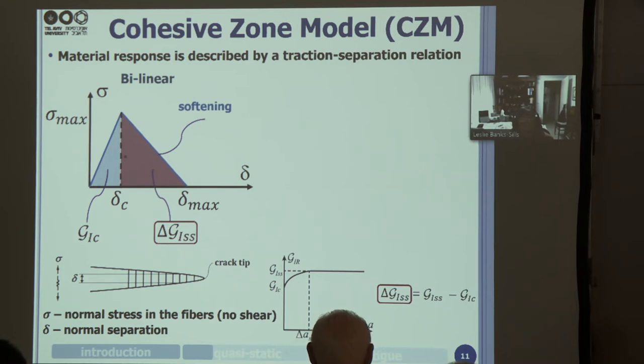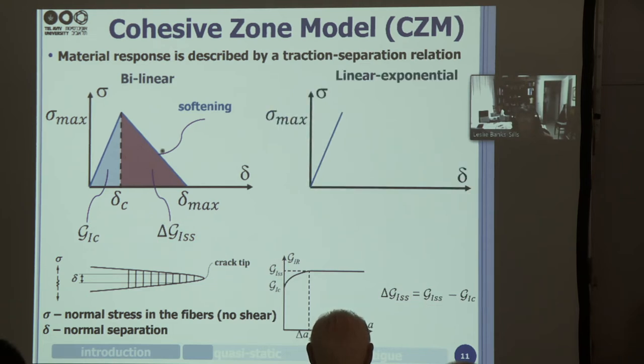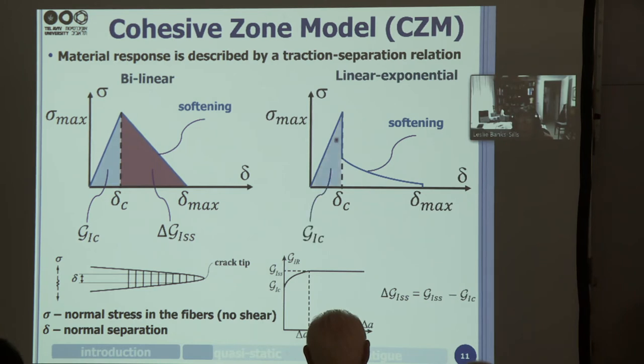We didn't use a bilinear curve, it wasn't suitable. What we did was we used a linear exponential curve where, again, we load up, we have a linear triangle here, and then the stress drops precipitously and we have softening, which is exponentially decaying. And again, G1C is the area in the blue region and delta G1SS is the area in the pink region. So this is our traction separation relation.